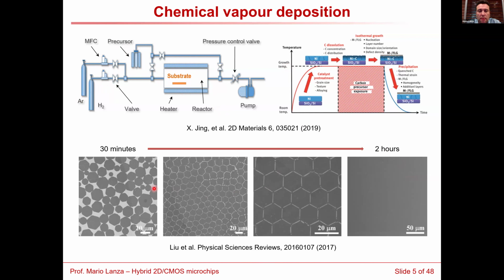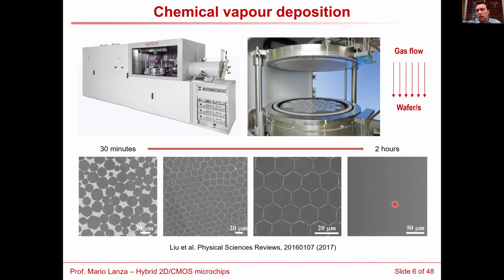And these are some SEM images of the sample during the growth process. First, you have the deposition of some seeds, then they start to grow laterally at high temperature until they merge, and then we have a continuous film. This has been demonstrated by many different authors. Most labs have a little tube with a diameter of 1 inch, 2 inch, or 3 inch, but this can also be done at the wafer scale.